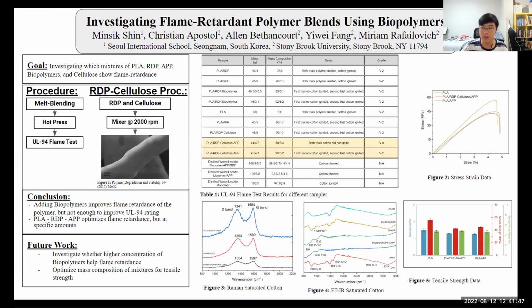Hello, my name is Minsik Shin. I worked on the flame retardant polymer blend using biopolymers. Our goal of this research was to investigate which mixtures of PLA, RDP, APP, biopolymers, and cellulose show flame retardance. The way we created those polymers was first by melt blending the desired polymer, and we used the hot press to make a stick-like mold. Then we subjected it to the UL94 flame test, which consists of two 10-second direct exposures to a blowtorch and a cotton below to check whether the cotton ignited or not.